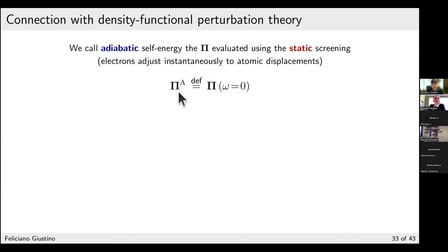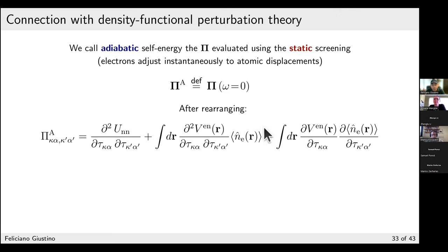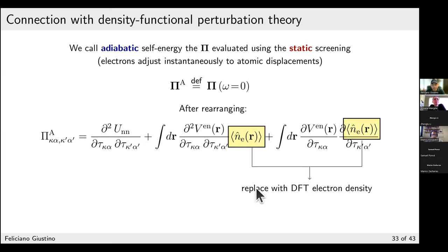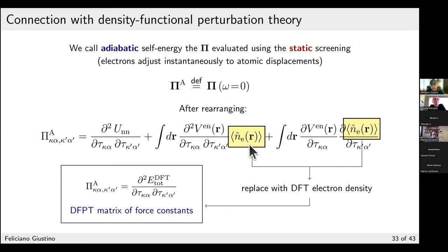Setting ω=0 in the self-energy simplifies the expression to exactly what you find in density functional perturbation theory, as reviewed by Baroni and co-workers. The interatomic force constants are given precisely by this expression — the only difference from DFT-based DFPT is that here the electron density is the many-body density, while in DFT it is the Kohn-Sham density. Everything else is the same. So the adiabatic many-body self-energy with the DFT electron density exactly recovers the DFPT interatomic force constants.